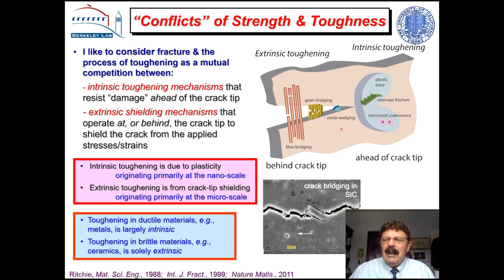Ceramics tend to be toughened by totally different mechanisms, which involve shielding the crack tip from the applied driving forces. These are mechanisms that operate at and generally behind the crack tip. They're associated with bridging, say, fibers or grains that would carry load that would otherwise be used to propagate the crack. There's a grain bridging zone in a ceramic, silicon carbide. These mechanisms operate basically in multiple length scales, whereas plasticity is generally generated at the nanoscale. So these are the intrinsic ones ahead of the crack tip, primarily for ductile materials, and extrinsic ones behind the crack tip, primarily for brittle materials.